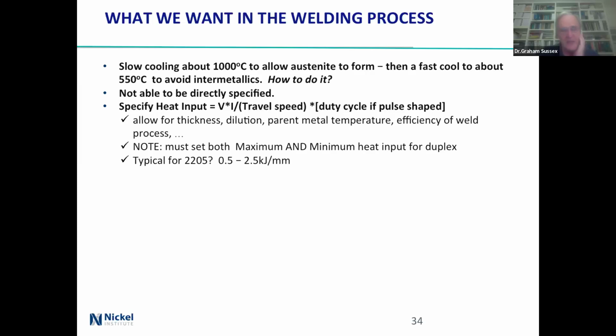And for duplex, you've got to give a maximum, and I'll show you a picture of it in a minute, but also you've got to give a minimum, because otherwise it cools down too quickly and you don't wind up with proper formation of the two phases. Typical for 2205, about 0.5 to about 2.5 kilojoule per millimetre.